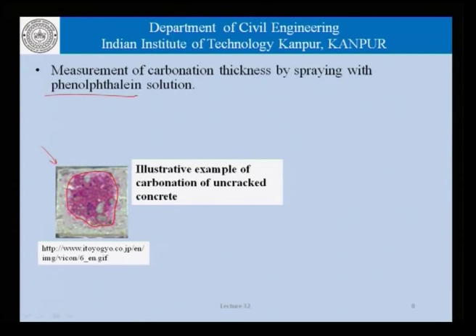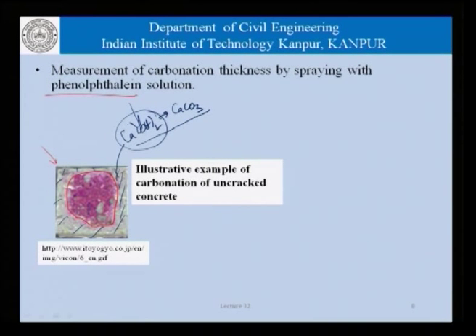which is pink. That is, this is the zone which has high pH, and there is this zone here which is colorless, and this is the zone where the calcium hydroxide has been converted to calcium carbonates. So, there is a depleted amount of, or there is a depletion in the levels of calcium hydroxide, and therefore, the pH in this portion here, where we can say that carbon dioxide has penetrated completely.